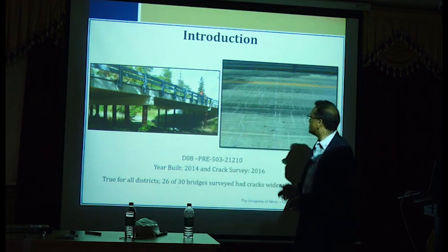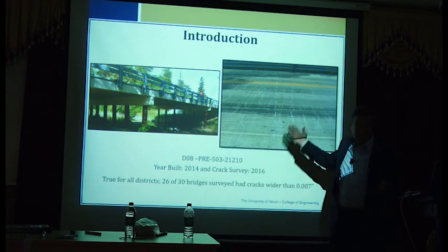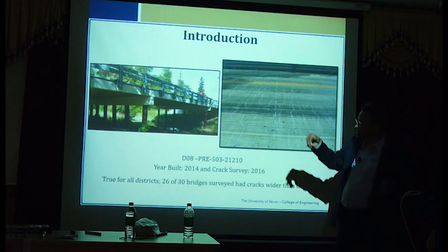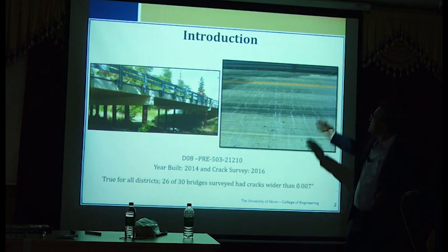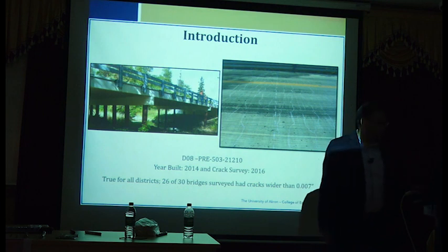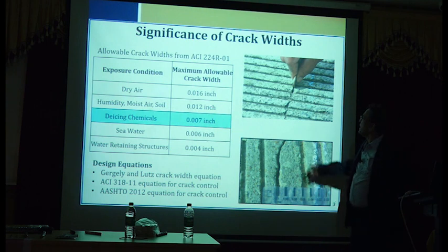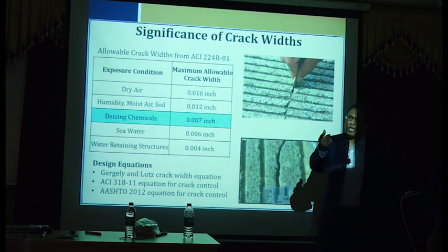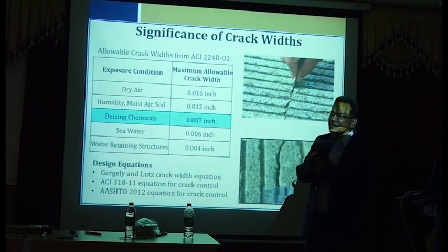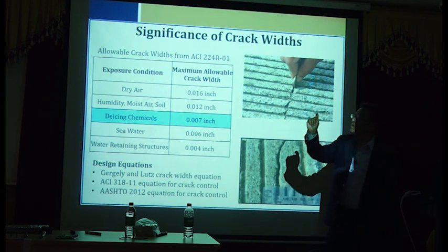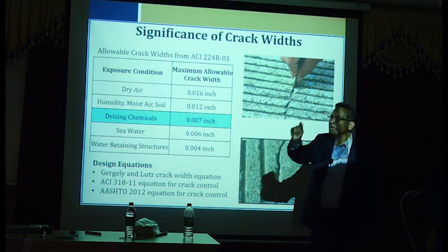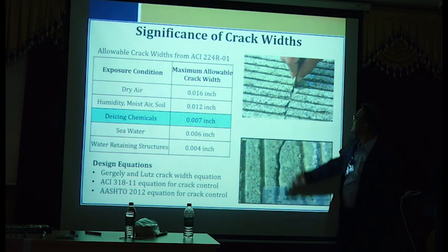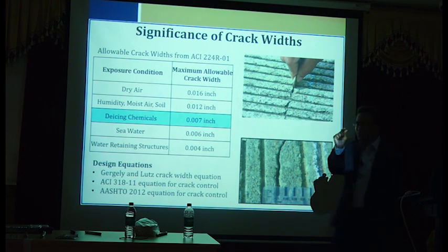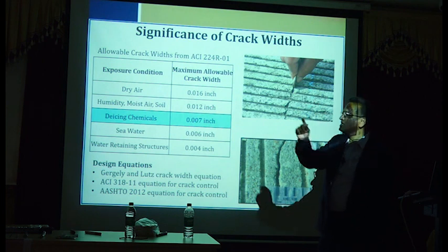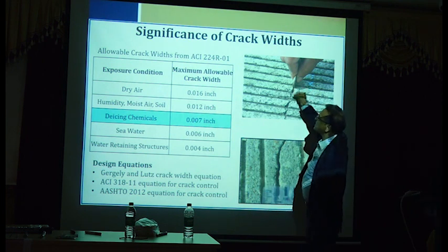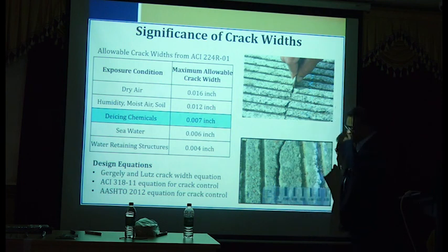That's the problem. So once again, Shrikant did all of this work. We go to sites, we do the actual inspections, and we look at the crack profiles, crack widths, everything. And if you see this one here, these coins are quarters. Like in India, we have coins. They have certain thickness, right? So the easiest way to show people is that's a 2-quarter crack. So 1 quarter is 1 coin, 2 quarters is 2 coins kept side by side, and you insert it, it's still very wide. So that's a very wide crack.